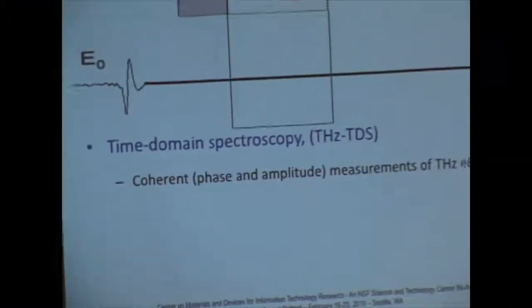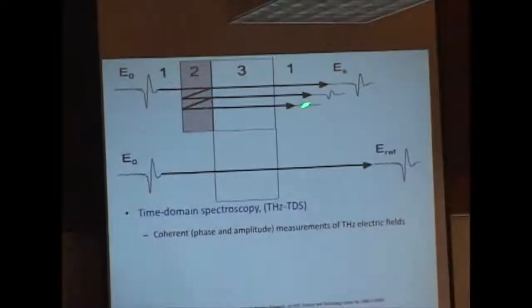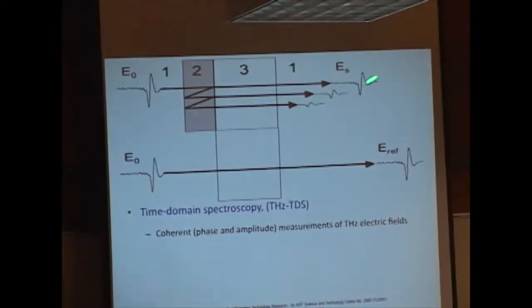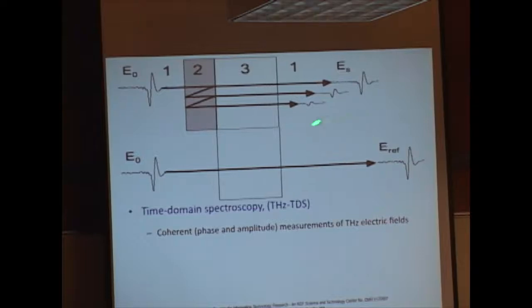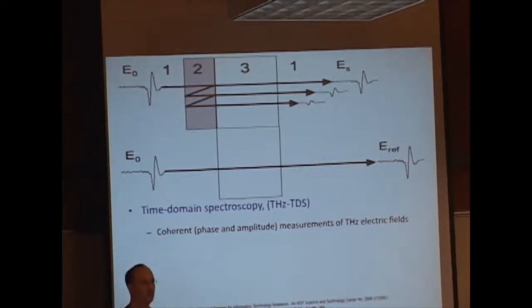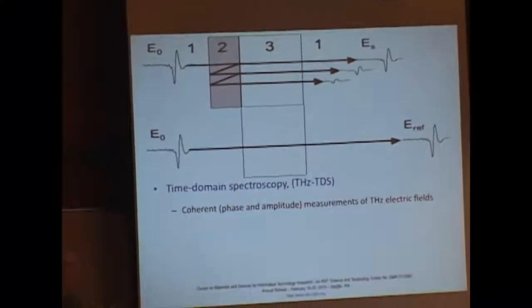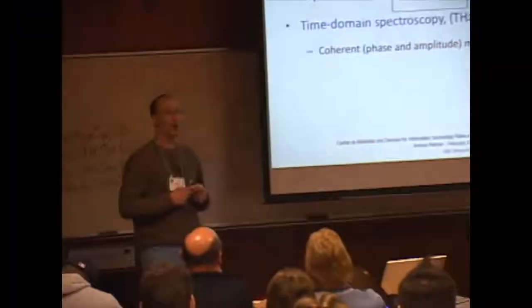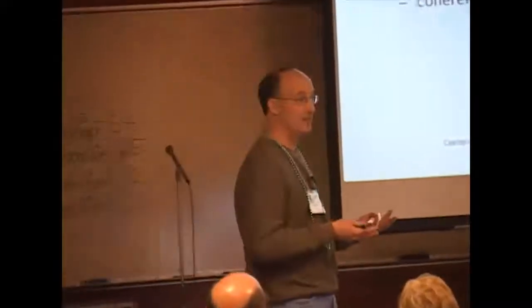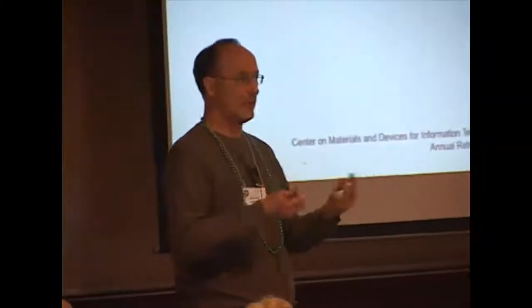You would send your terahertz pulse through your, say, substrate, and you have some reference. And then you send your terahertz pulse through your sample and the substrate. And notice that there's some reflections possibly, and that's a delay from this time. So that's a phase change. But then the amplitude is also changing. Because we have the phase and the amplitude in a coherent manner, we can extract the complete dielectric function of this material, both the real and imaginary parts of the index of refraction, or the real and imaginary parts of the photoconductivity if we're looking at semiconducting polymers or organic photovoltaics or something like that.